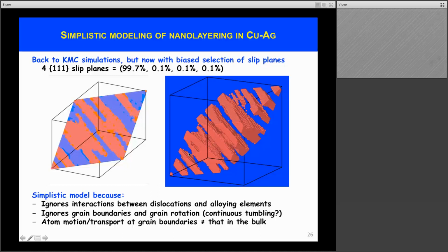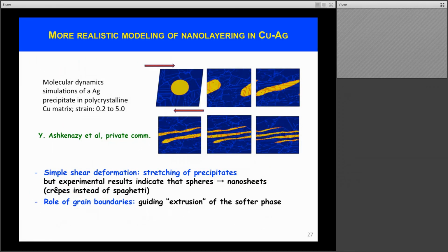So it helps us a little bit to understand how nanolayering can take place, but it's somewhat simplistic because it ignores interactions between dislocations and alloying elements. Here there are no grain boundaries, and grain boundaries play an important role. And so we have also used molecular dynamics simulation to have a more realistic understanding of this nanolayering reaction. We do see here the stretching of this silver ball in yellow in response to simple shear deformation and formation of layers, and it also illustrates the role of grain boundaries, that they can guide the extrusion of the softer phase, here silver.